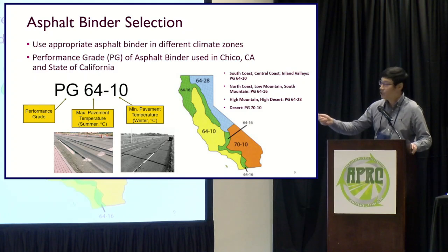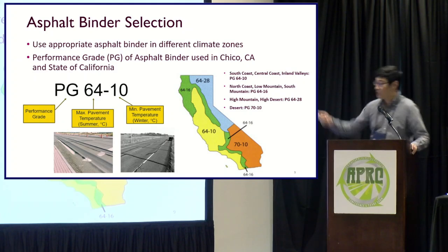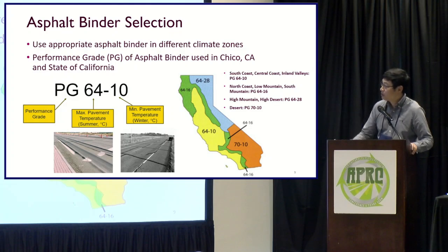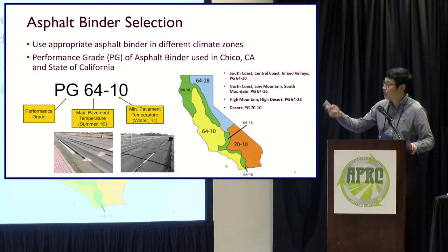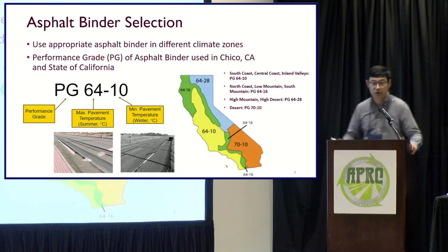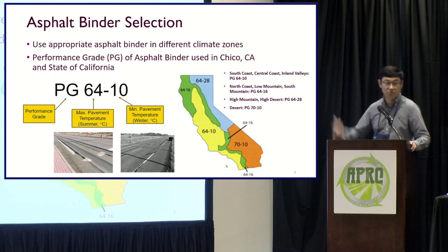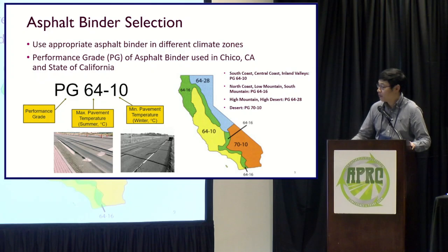If you look at the PG map, the performance grade of the binder used in California, for the South Coast, Central Coast, and the Inland Valley, Sacramento Valley, we use a PG 64-10. Caltrans recommends to use PG 64-16 in the North Coast, Low Mountain, and the South Mountain area. So you can imagine that area, winter is a little bit colder, right? High mountain area, high desert area, the performance grade is a PG 64-28, and in the desert area, it's bumped to the high performance grade, the PG 70. You can expect the summertime over there, PG 70-10. So that is the PG map in California.